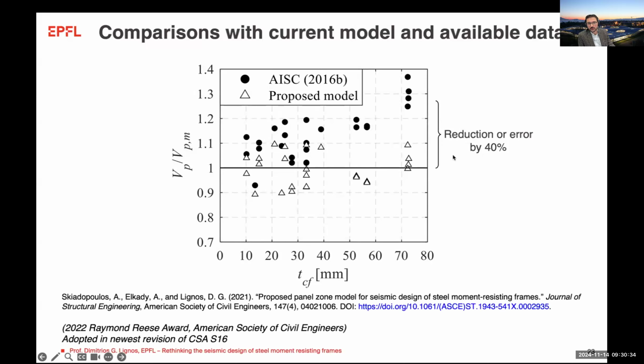And if I show you here, for instance, some of the comparisons I was showing before, where I'm comparing the prediction of strength on V_p versus the one measured in experiments, and I compare with what I'm getting with the proposed model, you see that even in the range of very thick flanges, I am able to reduce my error by 40%, and I can predict strength within a 10% error accuracy, regardless of the column flange thickness.